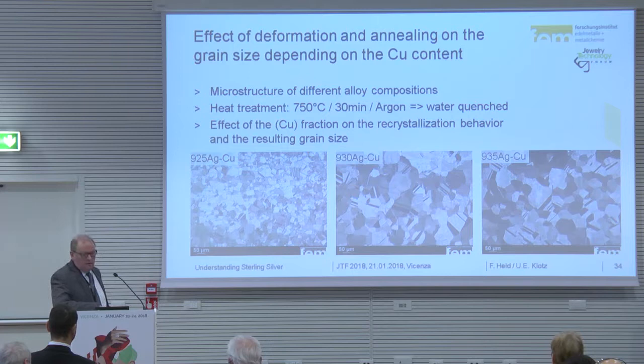Effect of deformation and annealing on the grain size depending on the copper content. Microstructure of different alloy compositions. Heat treatment is all 750 degrees, 30 minutes, quenched in argon. And you see, if we use 925, remember the diagram, you have the most copper phase in it, 930, 935, and you see the grain growing. And this also is for the orange peel effect.